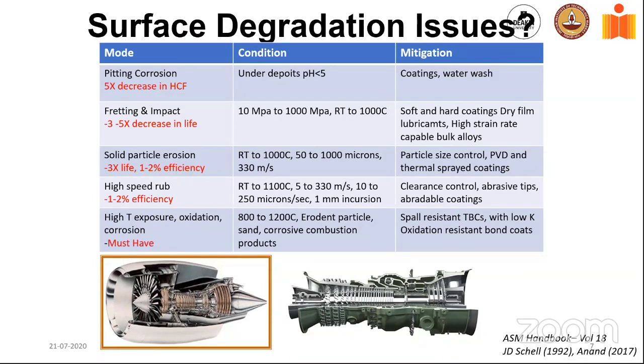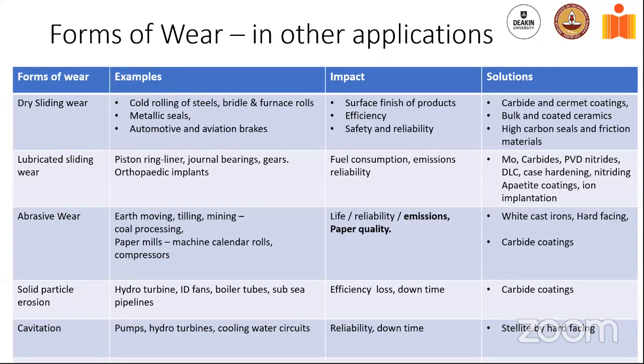But you can really have soft coatings. And these soft coatings essentially help in redistributing stresses. Along with the soft coating, you throw in a dry film lubricant. And this lubricant essentially reduces friction, reduces high-speed rub and wear, keeps the overall wear rates fairly low, because the lubricant in tandem with the soft coating works really well together to manage life and wear in aircraft engines. And you would often see similar strategies coming into play in some of the turbo machinery with steam turbines and gas turbines, especially the use of dry film lubricants. Solid particle erosion, we use PVD coatings and thermal sprayed carbide coatings. Clearance control, we have soft abradable coatings. And as far as high temperature is concerned, we use thermal barrier coatings.